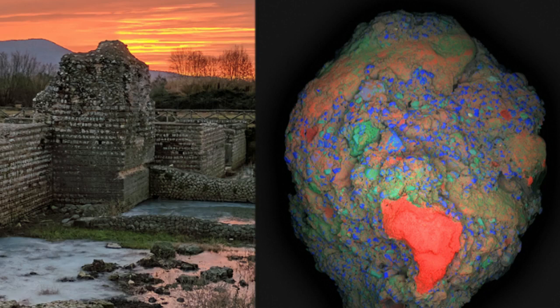An identical chunk of concrete made without quicklime never healed, and the water just kept flowing through the sample. As a result of these successful tests, the team is working to commercialize this modified cement material. It's exciting to think about how these more durable concrete formulations could expand not only the service life of these materials, but also improve the durability of 3D-printed concrete formulations. Through extended functional lifespan and the development of lighter-weight concrete forms, these efforts could help reduce the environmental impact of cement production, which currently accounts for about 8% of global greenhouse gas emissions.